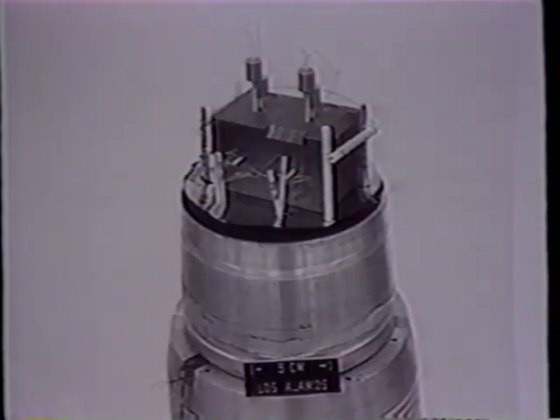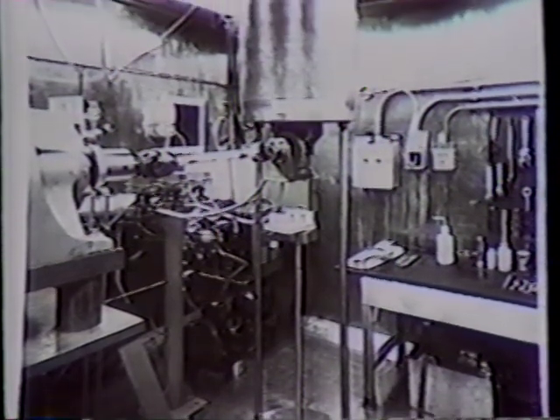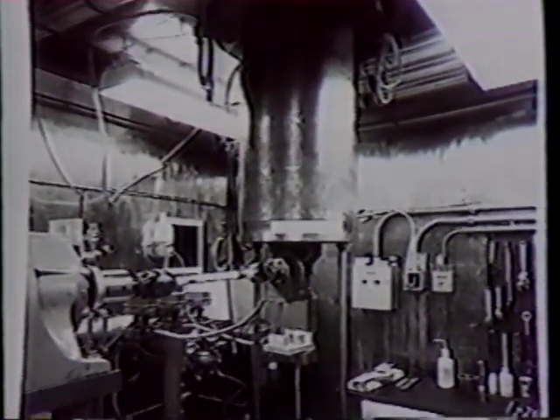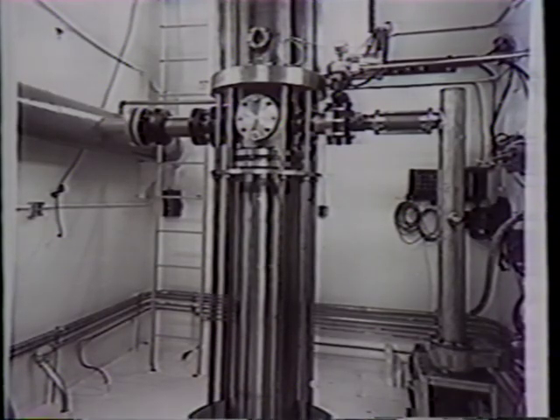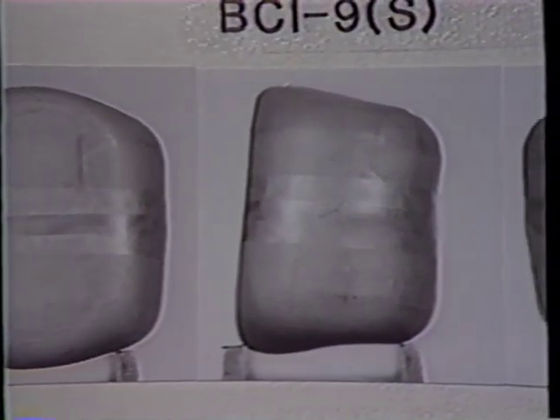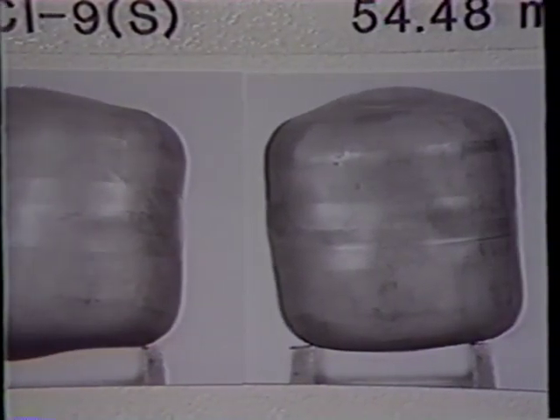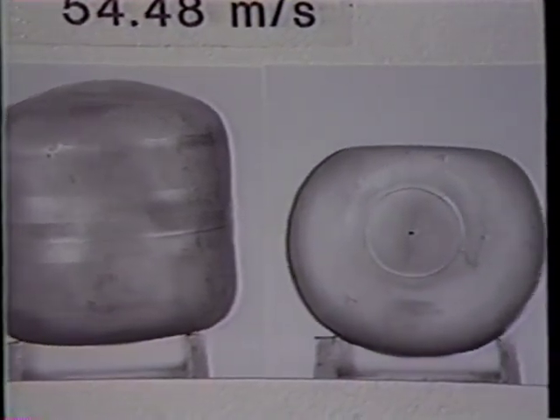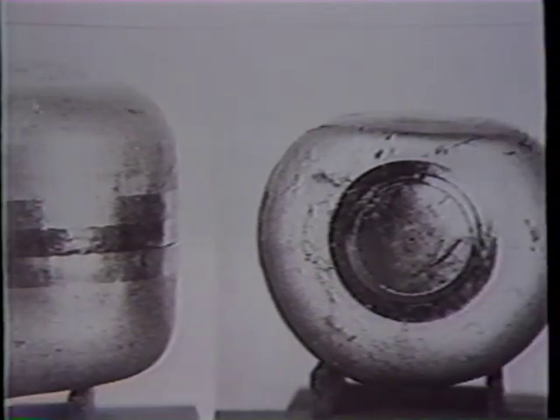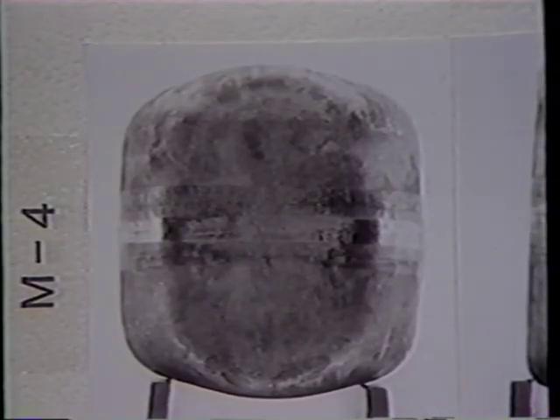Following an explosion or re-entry, the heat source components will eventually strike something, be it sand, water, or harder objects. Other tests evaluated the response of the heat source modules and fuel capsules to such impacts. Most of these tests were conducted in a special gas gun built at Los Alamos. The tests showed no breach of the cladding at the terminal velocity of the modules. For the most likely targets, sand, soil, or water, the capsules have demonstrated a capability to survive impacts at velocities in excess of 820 feet per second, well beyond any calculated impact velocities associated with Titan Centaur accidents.